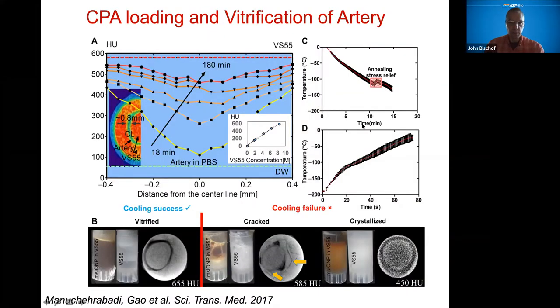This is just showing some of the characterization we did. The cooling here allowing us to get cooling rates that are above the critical cooling rate, plus we added in an annealing step to relieve some of the stress so we don't crack. And then the warming rates you can see below that, also above the critical warming rates needed. You can see our failure modes in the bottom as well as success. So vitrification success on the left, and then failure modes by either cracking or crystallization or both on the right.